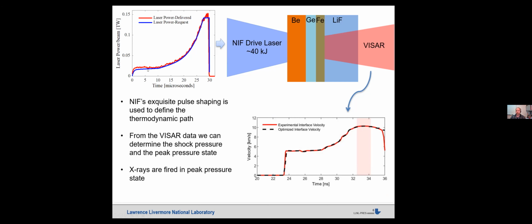So we have a sort of a flat foot that drives the shock. And then we have this gentle and increasing rise in intensity, which correlates with the ablation pressure, and thus the gentle increase in pressure until we reach our peak pressure state, and then we can hold that pressure state and pulse it with diffraction. So again, this type of laser profile incident on the beryllium ablator transmits a compression wave through the beryllium, the germanium, the iron.